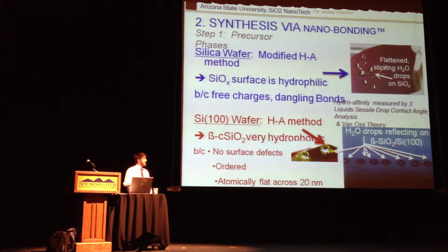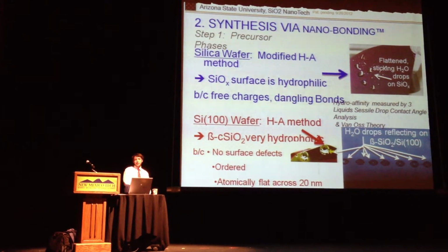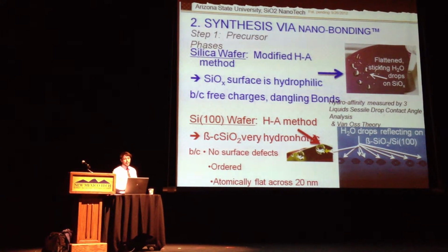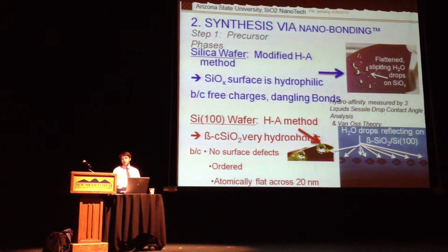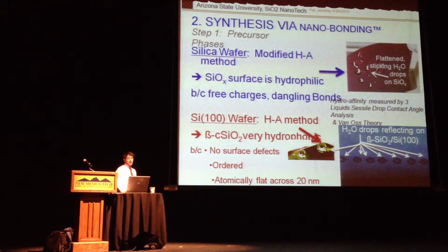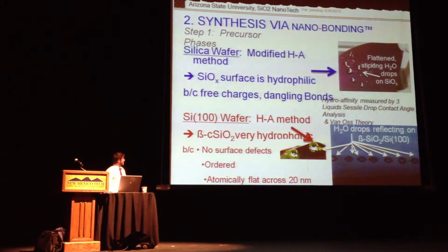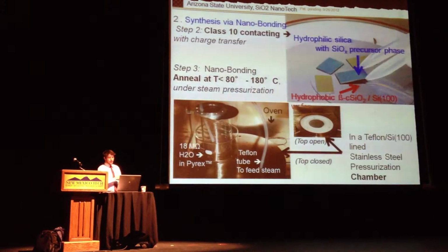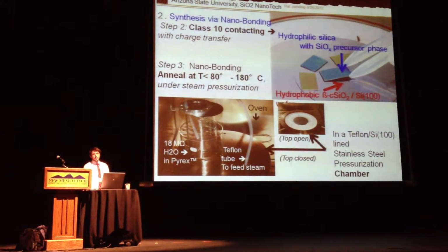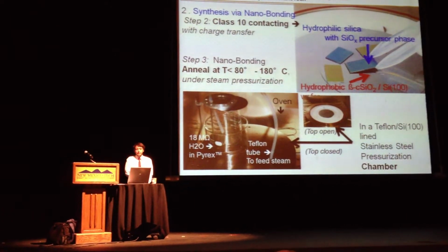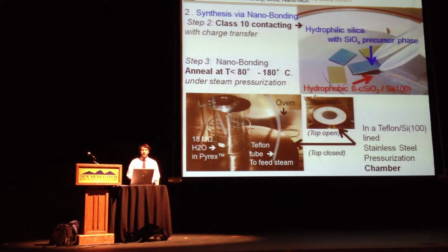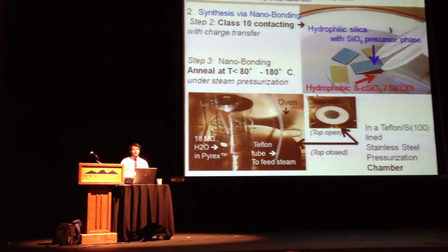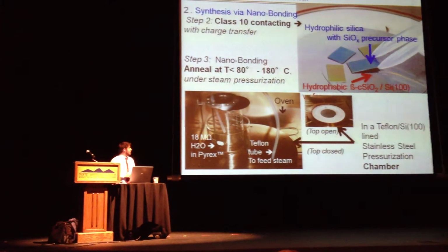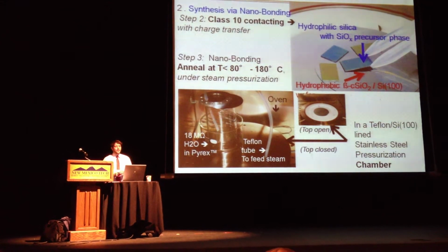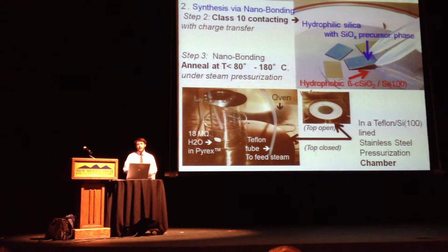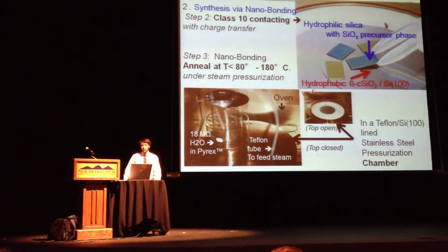Okay. Another evidence for this is then the hydrophobicity or hydrophilicity of the wafer. Our dangling bonds are going to attract liquids like water, while our ordered surfaces are going to repel and create more hydrophobic droplets on the surface. Okay. And then the actual synthesis occurs in a class 10 clean room and hood, where we contact the surfaces that have been prepared with both precursor methods, and then the application of steam in order to create an optimized humidity for the bonding process.